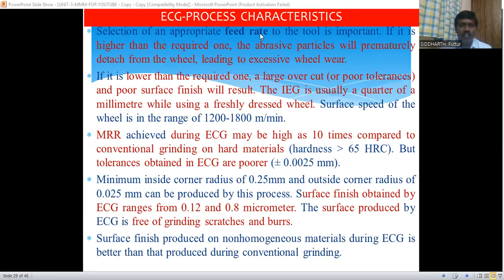The selection of an appropriate feed rate to the tool is also important. Means how fast a feed rate we are going to give in this electrochemical grinding process is very important. If it is higher than required, the abrasive particles will prematurely detach from the wheel, leading to excessive wheel wear. It is not going to remove more material, and finally excessive wheel wear takes place, meaning the tool life will be reduced. If it is lower than required, a larger overcut will occur, meaning the wheel stays longer on the surface of the workpiece and removes more material. Finally, if the metal removal rate increases, poor surface finish will come into the picture.